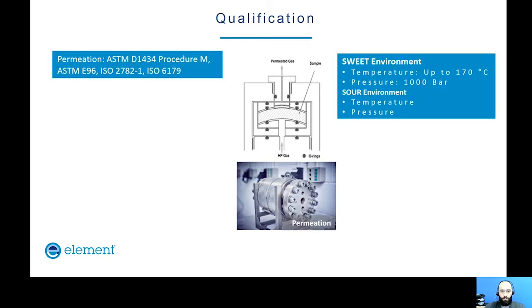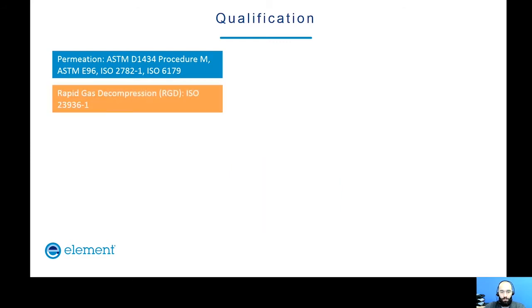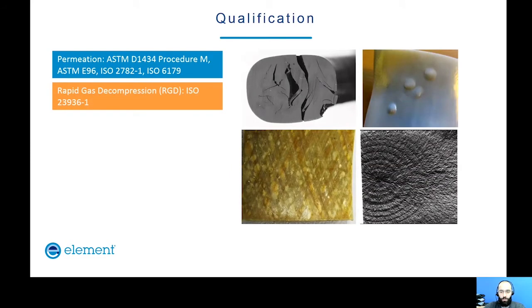Okay, now we're moving alongside the qualification program. It is always easier to try to break down what we're going to qualify. So as we said originally, the TCPs have two main sections. The liner, which keeps the fluid inside the pipe and away from the fiber reinforced composite body, and hence the important parameters to be tested are the permeation of the fluid through the liner and the gas escape when pressure drops, which can result in a structural damage illustrated here, ranging from blistering to cracking both composites and the liner.